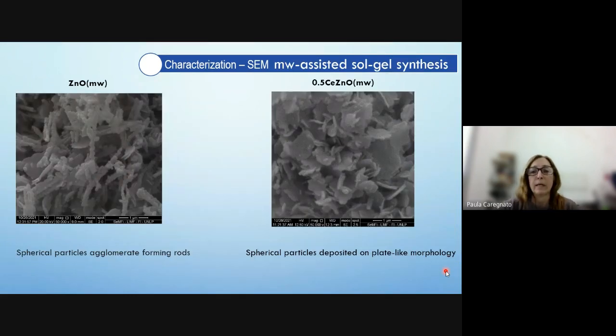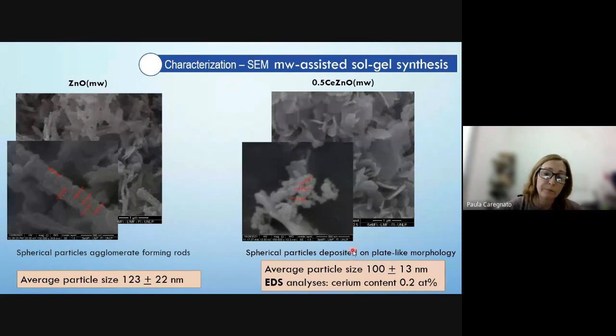Here are the scanning electron microscopy images of the materials obtained by microwave synthesis. We can see that the one without cerium has spherical particles which agglomerate, forming rods, and in the catalyst that contains cerium, we see spherical particles that were deposited on a plate-like morphology. The average particle size was measured, and we can see also that with cerium content, the average particle size decreased. By EDS analysis, the cerium content was 0.2 atomic percent.